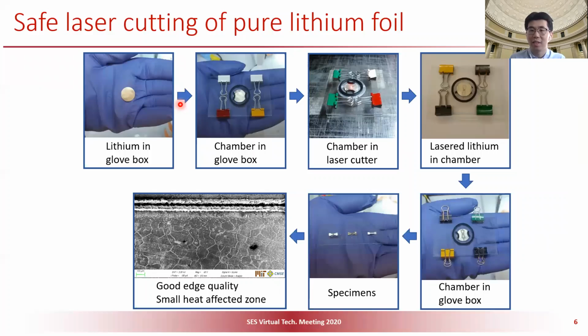So of course, there will be a heat affected zone, right? So this is the edge. We can see the edge is of very high quality, and the heat affected zone, as we observed, is less than 1 grain size. So we think that the heat affected zone is really small. And we also performed tests to validate that. We see that samples with laser cutting or with die cutting show similar test results. So we can safely say this cutting technology is very reliable.